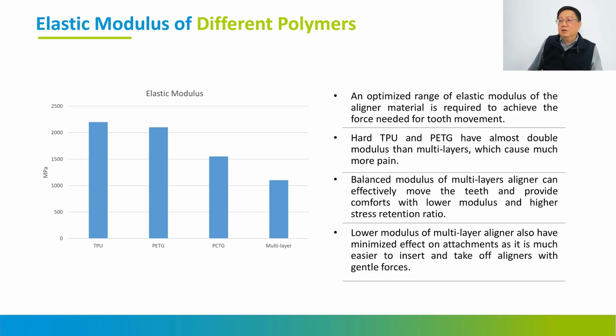How to balance the modulus, with more effective movement of the teeth and comfort with lower modulus, is very important. Also, the lower modulus has minimal effect on attachments, because higher modulus means that when you take the aligner out and wear it on your teeth, it is more difficult to wear. Then there will be problems, with more force on the attachment. Also, during the treatment process a few weeks later, because attachments normally stay on the patient for a longer time, not like a liner, each movement carries a big risk of the attachment being abraded, and maybe dropping off your teeth. They need another treatment to adhere a new attachment.